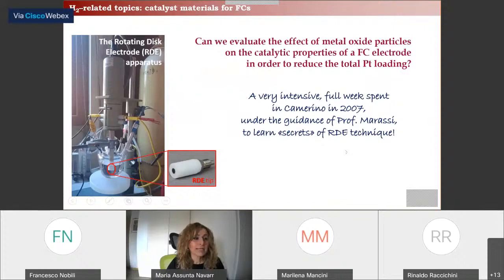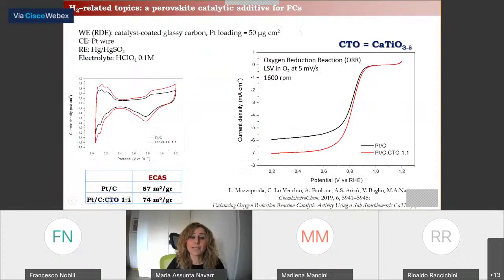So as a catalytic material for fuel cells, we were recently investigating the perovskite calcium titanate, which was demonstrated to be a good co-catalyst when added to platinum. Indeed, when it's used together with platinum, the electrochemical surface area of the catalyst really improves, and also the oxygen reduction reaction is enhanced. These improvements are probably due to oxygen vacancies present in the structure and in the stoichiometry of the perovskite.